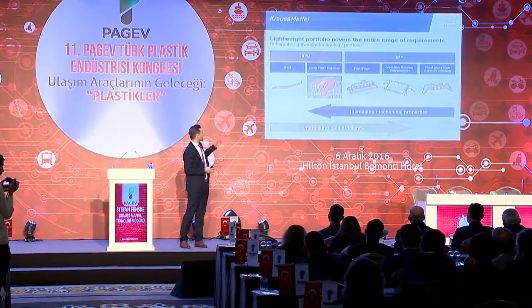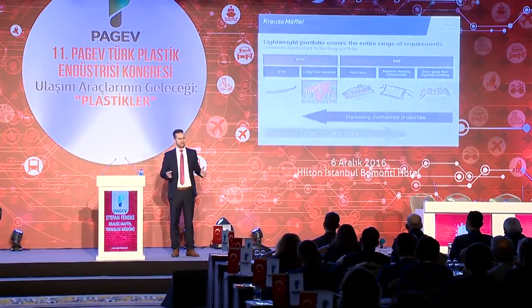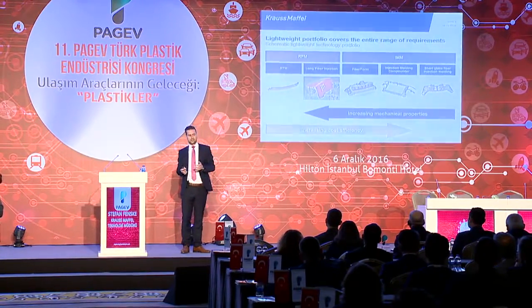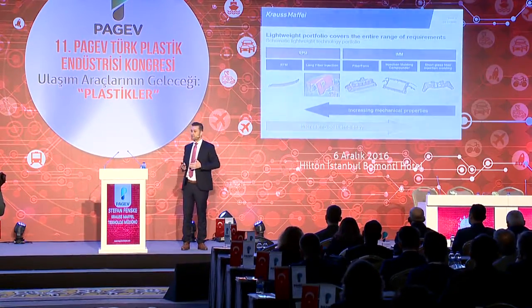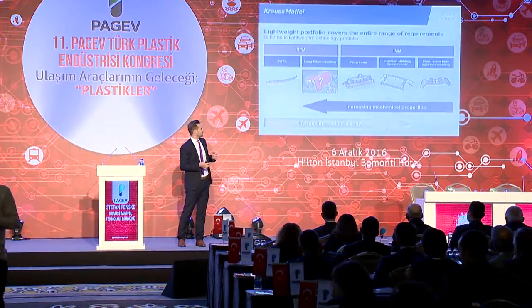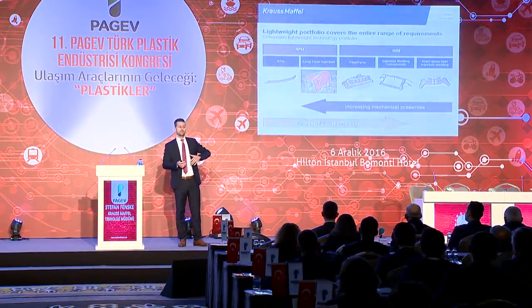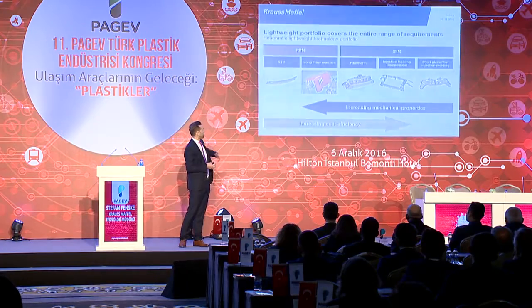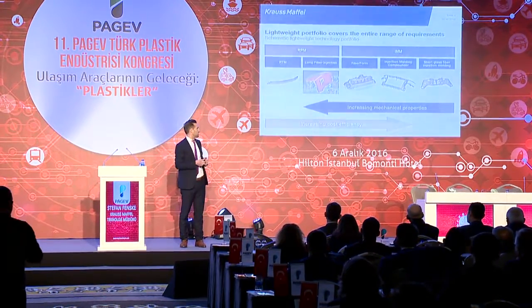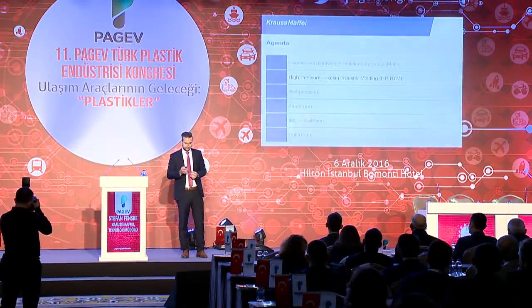These resin transfer molding technologies and parts, of course, we just heard it, give you excellent mechanical properties, but at the same time, the cost efficiency is limited due to the curing time of your resins. On the other side, injection molding gives you limited mechanical properties, but at the same time, a very good cost efficiency. And we also have this Fiberform technology, so organosheet back injection, which gives you the best out of two worlds, I would say.